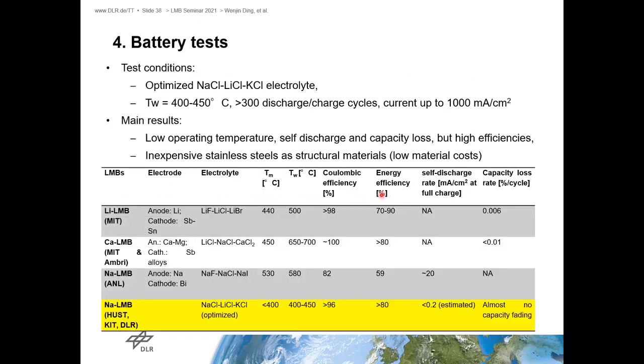Our partners in China did the battery test using the selected molten salt electrolyte. At first we used the sodium chloride salt mixtures, with a working temperature of 400 to 450 degrees C, more than 300 discharge and charge cycles, and a current up to 1000 milliampere per square centimeter. Our main result is that using the optimized salt mixtures, the sodium liquid metal battery can be used at low temperature, much lower than the conventional, state of the art liquid metal battery.